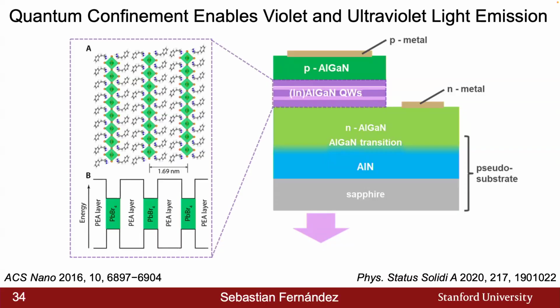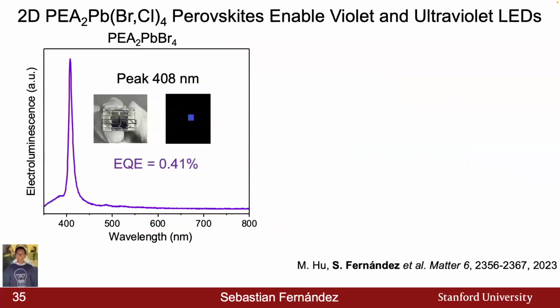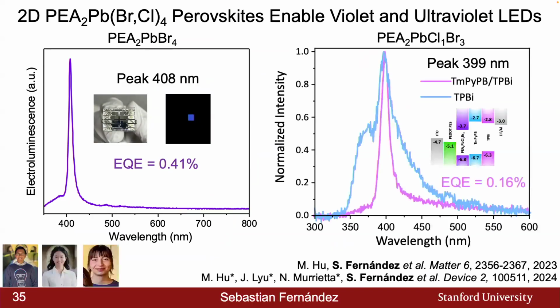And I will briefly show some of the work that was done within this group towards moving towards the ultraviolet spectrum. From here, majority led by Manchin, we looked at how we can use this phenethylammonium lead bromide layer, which hopefully many of you saw at Manchin's defense a few weeks ago, in which we can yield 408 nanometer violet light emitting devices with an efficiency of around 0.41%. By exchanging just a little bit of the bromide with chloride within the system, we can also push towards the ultraviolet spectrum by having a 9 nanometer blue shift, showcasing the first ultraviolet light emission from these lead halide perovskite materials.